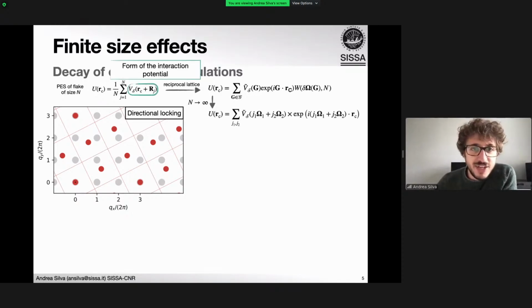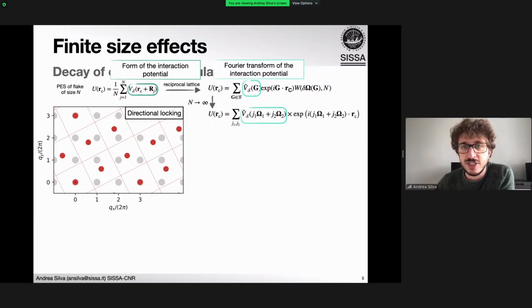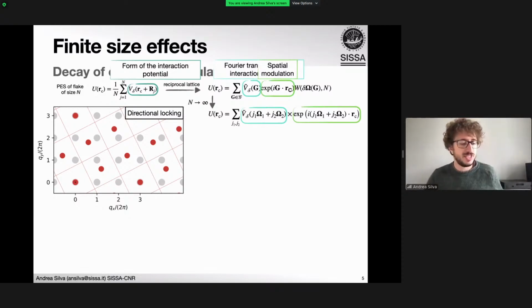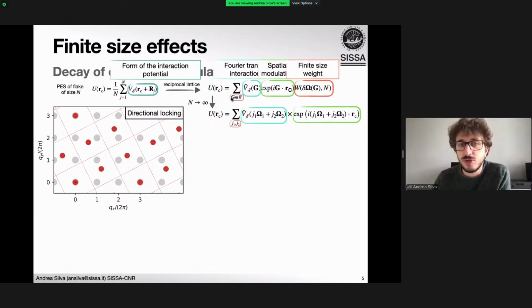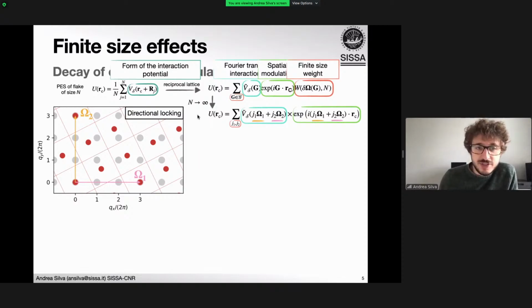The important bit is that here we have an arbitrary form of potential, which just needs to be periodic, and we can write equivalently the system in the Fourier space. The spatial distribution is given by these plane wave terms here. And at finite size, we have this weight. So all the Fourier components, which means any possible modulation of the corrugation, enter the system, but they are weighted by the specific shape and size of the flake. And in the infinite limit, this needs to give back the categorization I explained before, because this weight will just select the relevant Fourier components, which here are these matching vectors defining the moire pattern of the system. At finite size, other components can contribute as well.